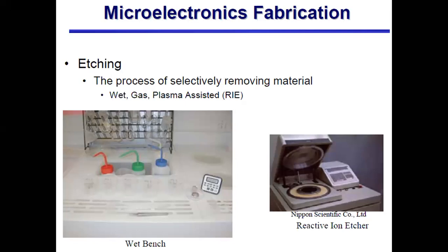The hit and trial method is that you dip your wafer in the HF solution, and after, let's say, 30 seconds, you take out the wafer, wash it with DI water, dry it with a nitrogen gun, and then under the microscope visualize whether all of the silicon dioxide layer has been etched or not.